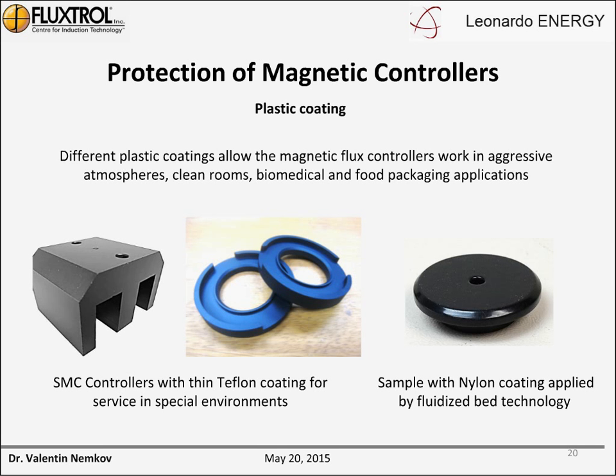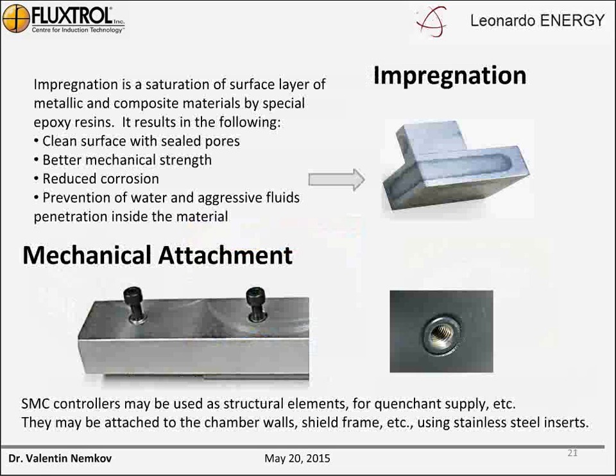On the right side, you have a sample of material coated by nylon using fluidized bed technology, but electrostatic powder coating could also be applied very successfully. I want to mention one more method of improvement of properties of ready-to-use parts. It's impregnation. Impregnation is a saturation of a surface layer of metallic or composite materials by special epoxy resin under high pressure. It results in the following: clean surface with sealed pores, with better mechanical strength, reduced corrosion, and prevention of water or aggressive fluid penetration inside of the material.